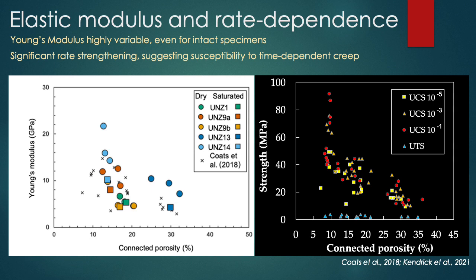Here, I also want to draw attention to a previous study of ours in which we performed a series of compressive strength tests at a range of different strain rates and showed that the Unzen lavas are rate strengthening, or, in other words, that they're susceptible to time-dependent deformation, becoming weaker at longer stressing durations, as is typical of geomaterials. So this is also an important consideration when thinking about lava dome stability.